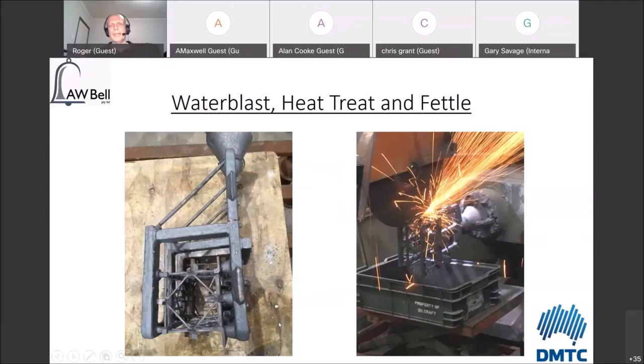The reason being, and the reason why I've put heat treat in the middle here, is that you actually must heat treat these parts while they're still on the tree, just because the walls are so incredibly thin. Basically, there is no structural strength at high temperature when you're only at 1 millimeter or so. So if you want your casting to not move around too much, you've got to heat treat it still attached to the tree. So you heat treat it on the tree, and then once it's off the tree, take it and fettle it, cut it all off with an abrasive cutoff wheel. You can see the cutoff wheel on the right-hand side there as we're removing the runner system.